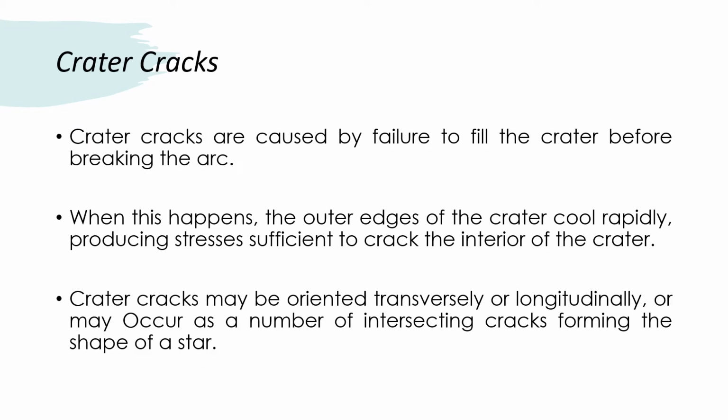Next one is crater cracks. Crater cracks are caused by failure to fill the crater before breaking the arc. When this happens, the outer edges of the crater cool rapidly, producing stresses sufficient to crack the interior of the crater. Crater cracks may be oriented transversely or longitudinally, or they may occur as a number of intersecting cracks forming the shape of a star.